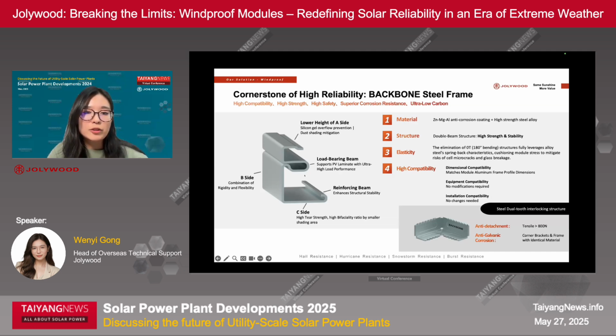And we have this specially designed double beam structure. We have this load bearer beam here to support the laminates and provide very good loading performance. And we also have this reinforcing beam at the C side. With this reinforced beam, we can have a thinner thickness with the same strength and a shorter C side, which will lead to a smaller shading area at the back side. And it can actually provide a higher bifaciality ratio.